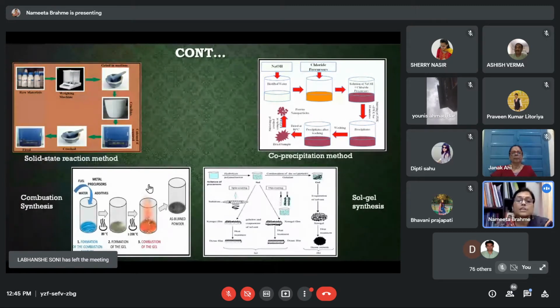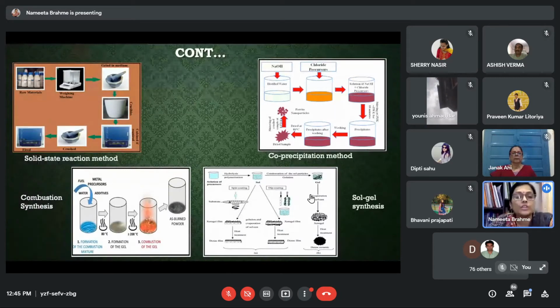The second is the combustion synthesis. This synthesis is based on the principle of exothermic reaction. Here all the raw materials and fuel are calculated and weighed in a stoichiometric ratio and mixed in an agate mortar pestle until the mixture is converted into a thick paste, and this paste is placed in a preheated furnace, which is about 500 to 700 degrees centigrade.